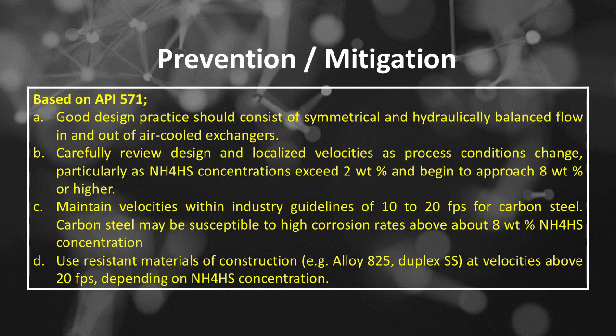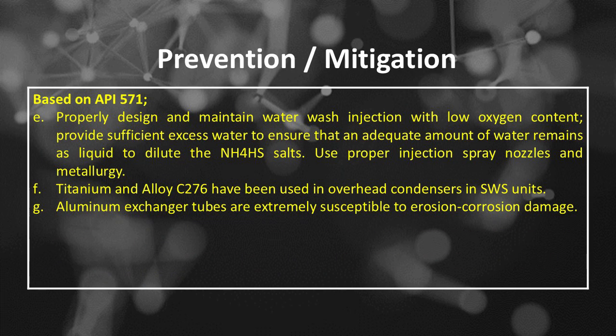Number D, use resistant materials of construction, such as alloy 825 or duplex SS, at velocities above 20 feet per second, depending on NH4HS concentration. Number E, properly design and maintain water wash injection with low oxygen content, and provide sufficient excess water to ensure that an adequate amount of water remains as liquid to dilute the NH4HS salts. Use proper injection spray nozzles and metallurgy. Number F, titanium and alloy C276 have been used in overhead condensers in SWS units.